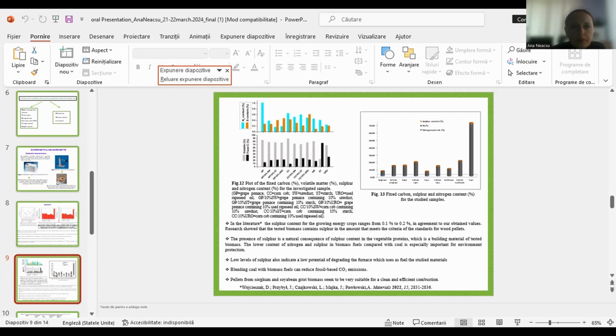In figure 12, we have plotted the fixed carbon content, volatile matter, sulfur, and nitrogen content for the investigated samples. And also in figure 13, the fixed carbon, sulfur and nitrogen content. Knowing the nitrogen content of biomass is important to assess nitrogen oxides that are air pollutants. So from figure 12, it can be ascertained that the presence of additives of 10% results in decreasing the nitrogen content of the investigated samples. The sulfur levels for control samples are lower compared to coal, making them emit less sulfur oxides than fossil fuel.